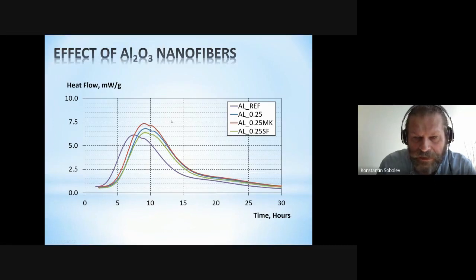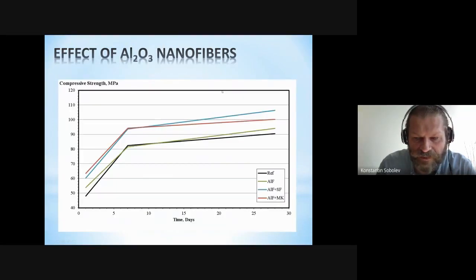And we also explored a combination of nanoalumina with metakaolin and also with silica fume. Again, relatively small quantities of these materials. And when we look at compressive strength development, again, civil engineers are really interested in compressive strength. So you can see black is your reference, and green is with nano alumina fibers.